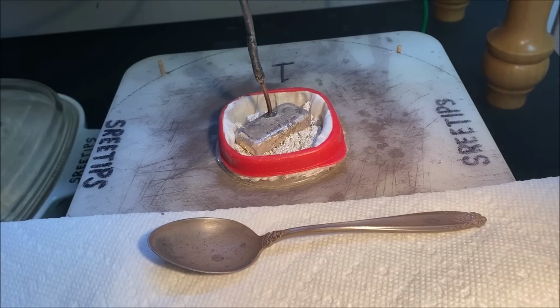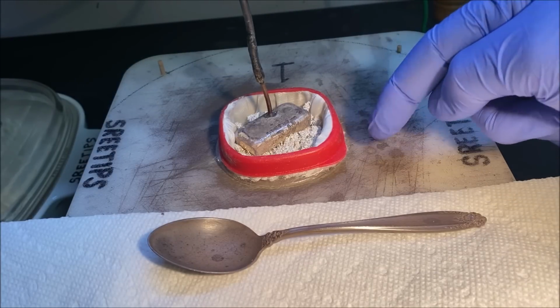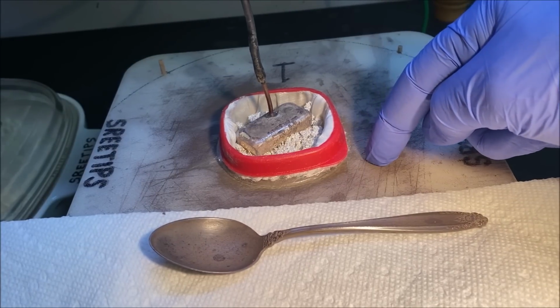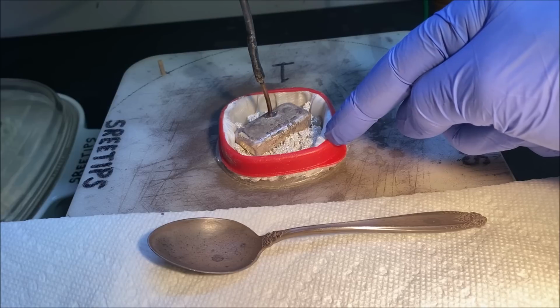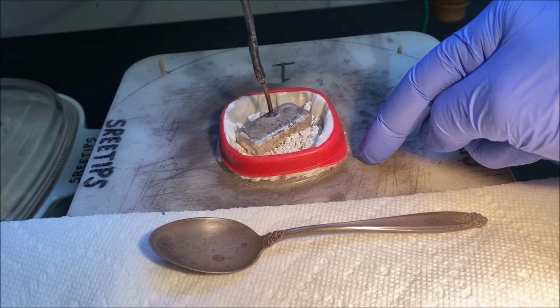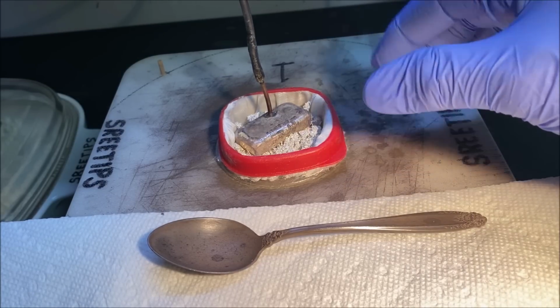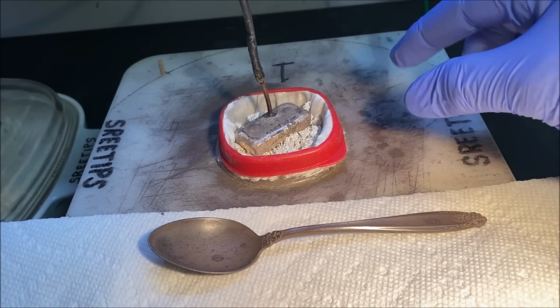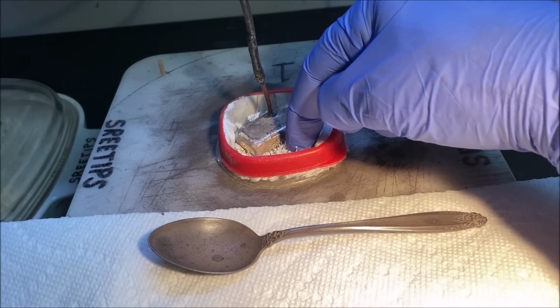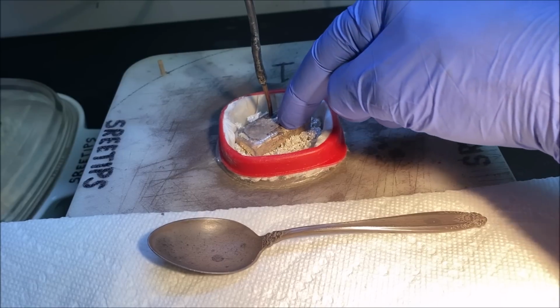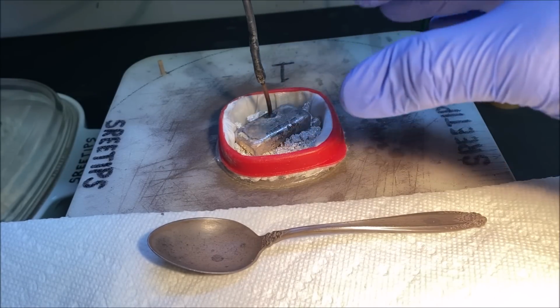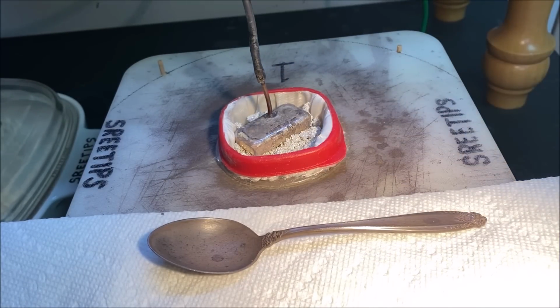So what it's doing is chewing up the silver down in the bottom of this basket that's in contact with the electrolyte, and then it just kind of chews all that away, and then it leaves a hollow spot. And since this doesn't push down in there well, then it just kind of suspends, and there's no more silver making contact with the electrolyte in the bottom of our anode filter.